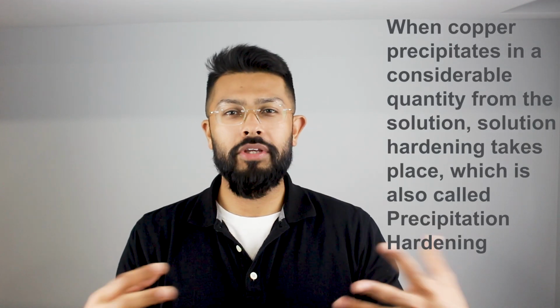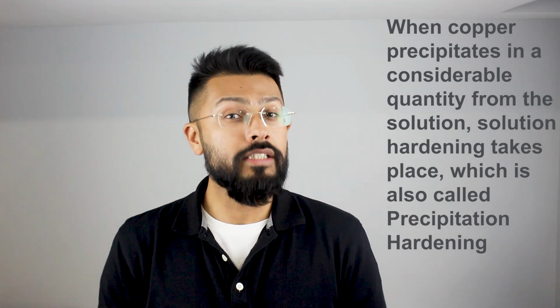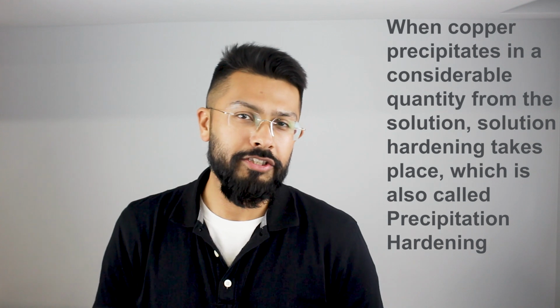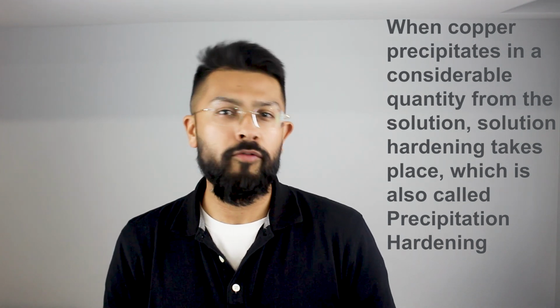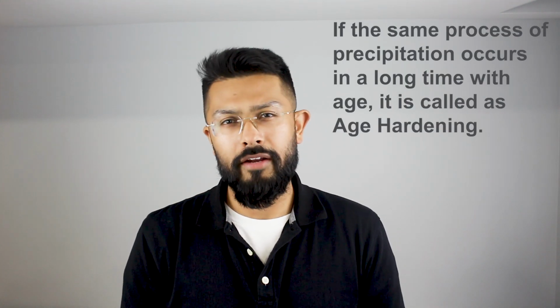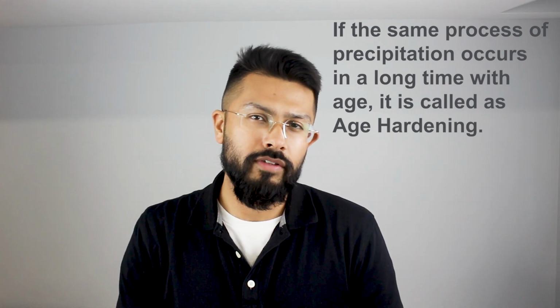It is possible to heat the alloy to a temperature at which the solubility is exceeded, but at which atomic diffusion is possible. In the temperature range 300 to 600 degrees, slow diffusion of copper atoms can occur. Given sufficient time in this temperature range, copper would begin to precipitate from the alpha solid solution. However, a significant hardening of the alloy takes place, presumably because the diffusing atoms have effectively prevented movement of the slip planes. This forms the basis of the precipitation hardening procedure used for type 3 and type 4 casting gold alloys. The same process may occur to a lesser extent and at a much slower rate at room temperature. Hardening which occurs in this way is referred to as age hardening.